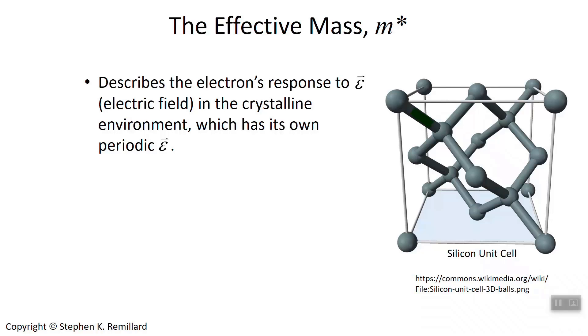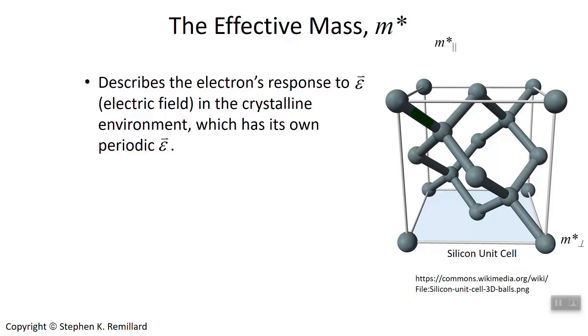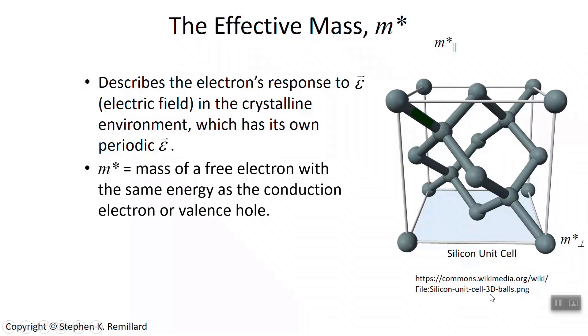As it passes through the crystal, depending on which direction it's going — here's a silicon crystal — we'll call this blue plane down here the perpendicular direction. Any movement in the blue plane is perpendicular to the c-axis, and any movement perpendicular to the blue plane is parallel to it. So we have essentially two directions: the in-plane direction, labeled as m-perpendicular, and the parallel direction labeled m-parallel. The star means effective mass. Because the electric field is a consequence of all the ions that the electron goes by, how the electric field environment appears in those two directions depends on the location of ions and the coordination of the crystal. That will cause the electron's acceleration to vary over space, leading to an average acceleration of the electron over space, giving it an effective, apparent mass, and it is different in those two directions.